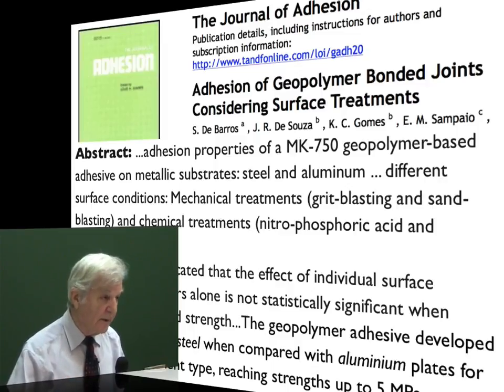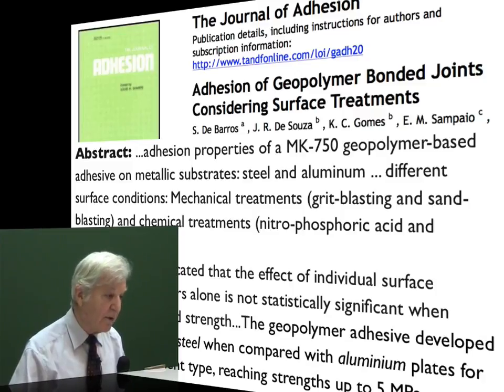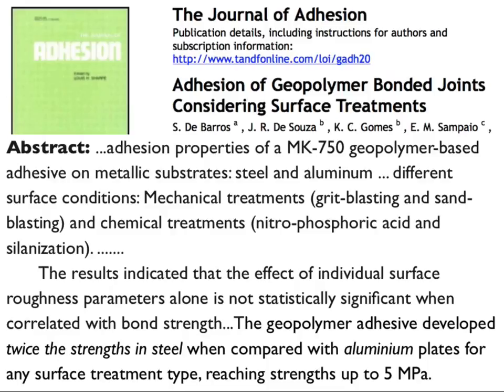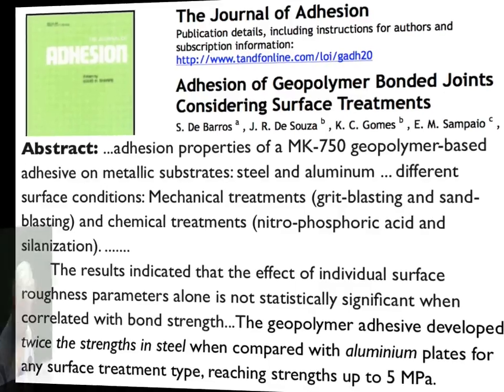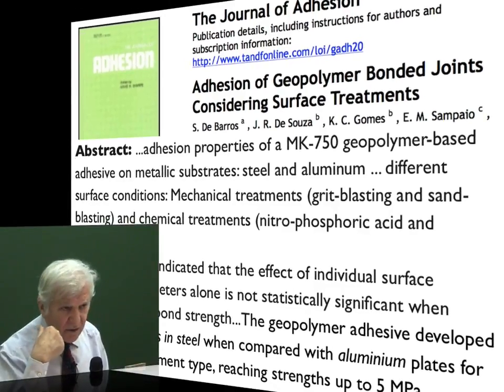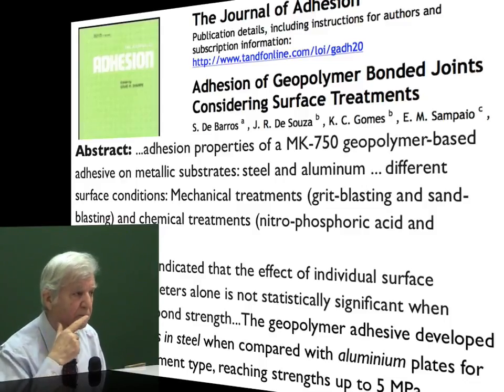So it's not the surface, mechanical surface, that is important from our point of view. We know that, having made several tests on adhesion on metal, what is important is the absence of any grease, oil on the surface. The geopolymer adhesive developed twice the strength in steel when compared with aluminum plates for any surface treatment type, reaching strength up to 5 MPa. So in fact, this is not a lot. What they achieved is medium.